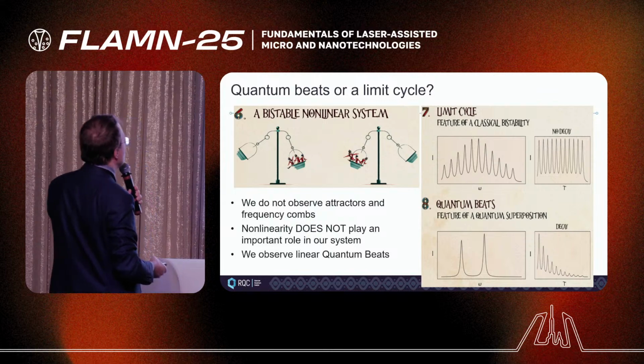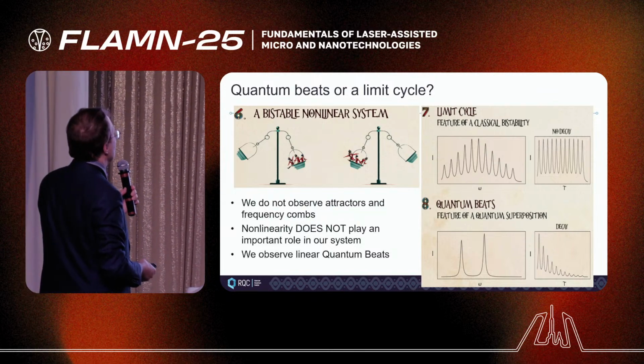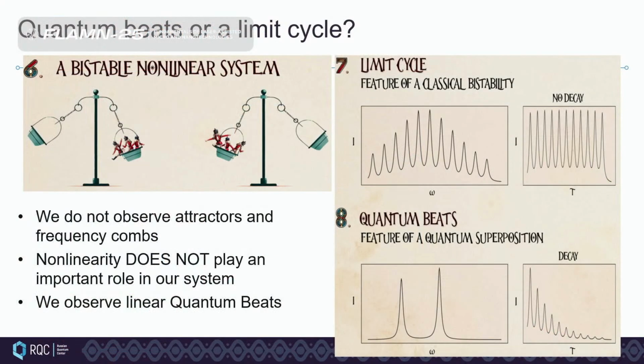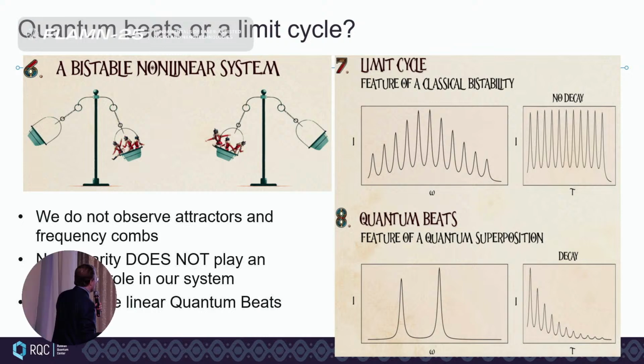These oscillations should be distinguished from the characteristic limit cycle behavior that is observed in many nonlinear optical systems. In a limit cycle, frequency combs should be observed, and the frequency of the beats depends on the nonlinearity. Here it is not the case. Nonlinearity does not play any important role here. The splitting, this frequency, is perfectly fixed by the geometry of the trap, and it is tunable. We can control it experimentally. We do not observe any attractors characteristic of nonlinear systems. We do not observe frequency combs.